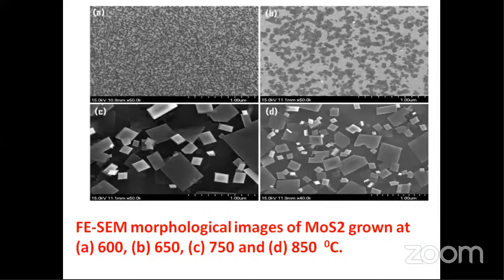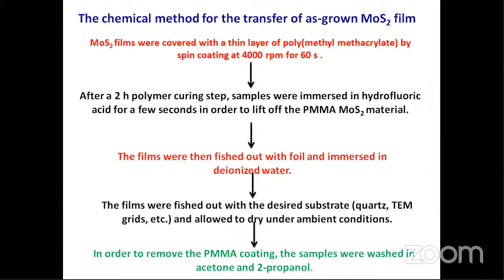Here we can see the high resolution scanning micrographs of MoS2 grown at different temperatures. At 600 degrees centigrade it is very thin, and as we increase the temperature of our substrate, the system agglomerates and looks like larger grain size of our MoS2 films. And this is the important thing.